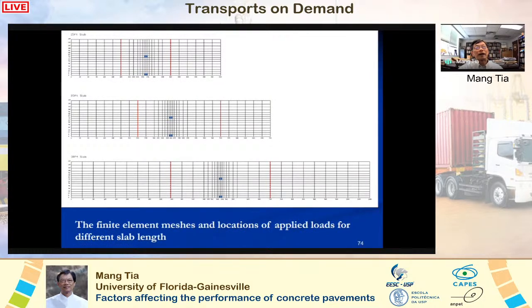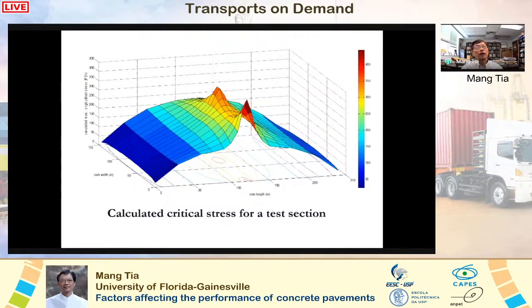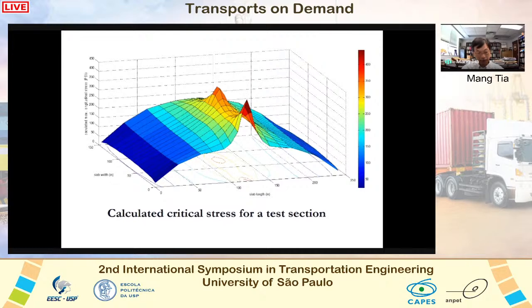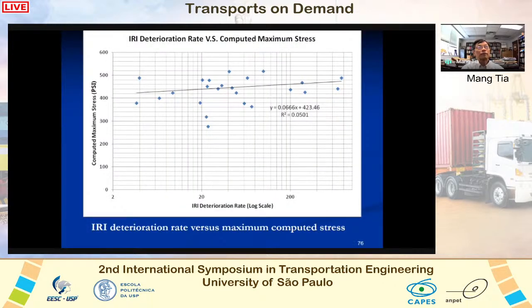This shows the finite element meshes used and the location of the applied load for the various slabs with different slab lengths. And this shows a plot of computed stresses from the critical stress analysis. Maximum stress from this analysis was used. The performance of the test sections was quantified by an IRI deterioration rate. The IRI deterioration rate was computed by dividing the change in IRI by the number of years and the average annual traffic in number of ESALs.